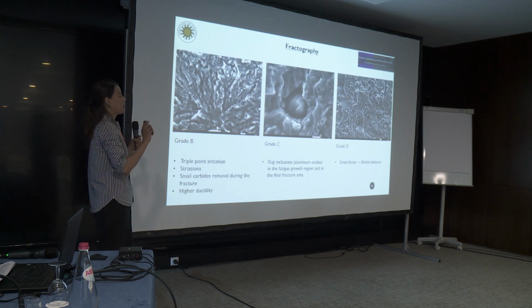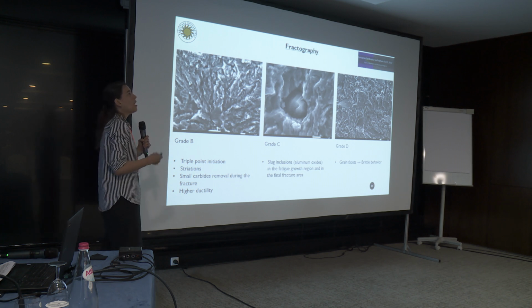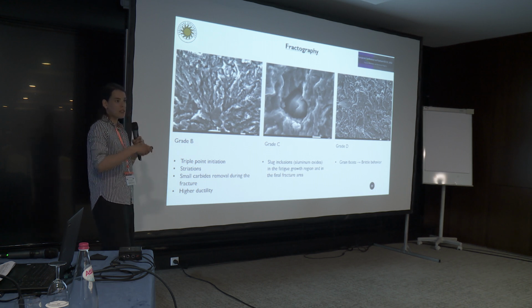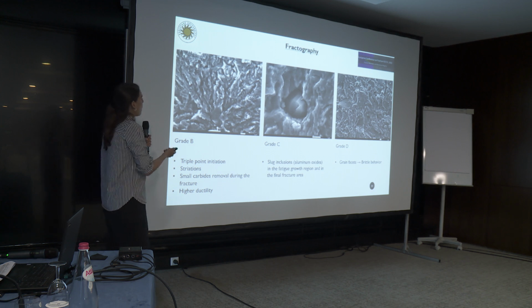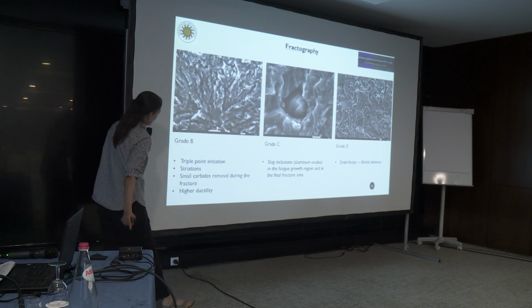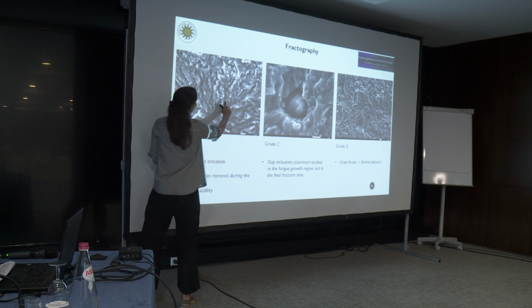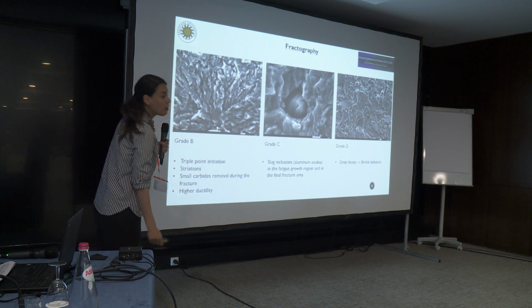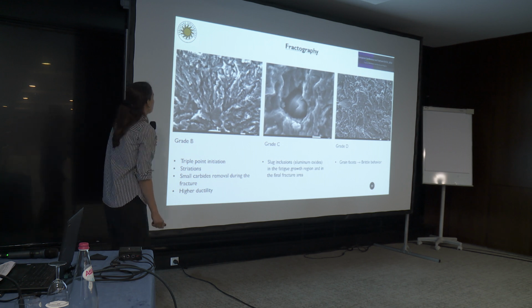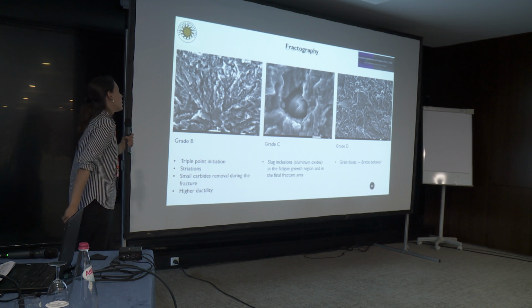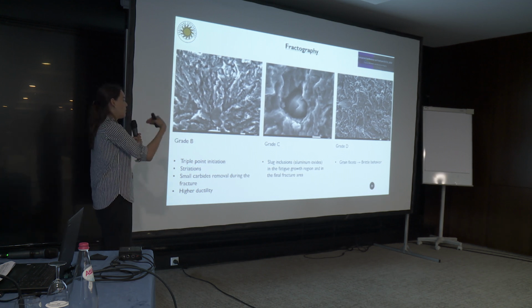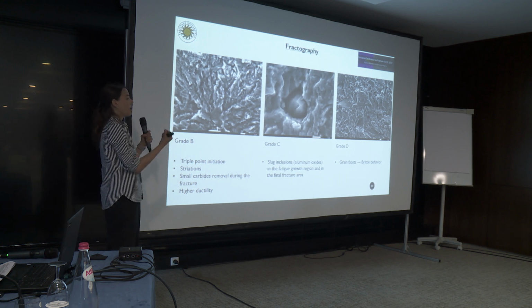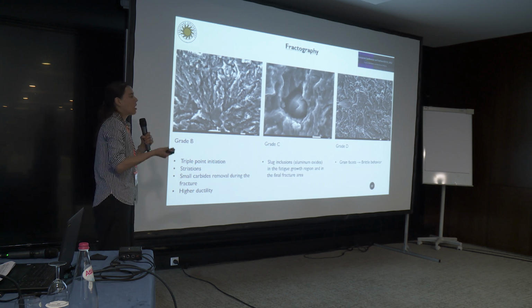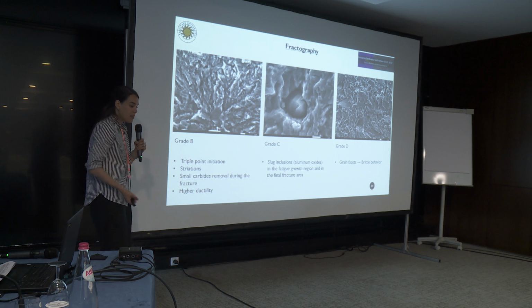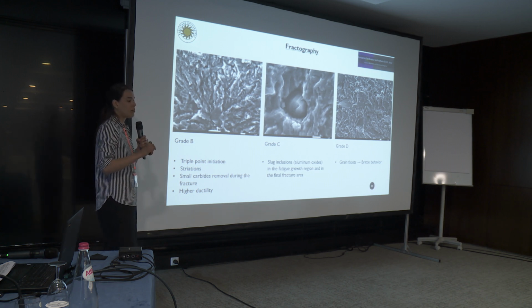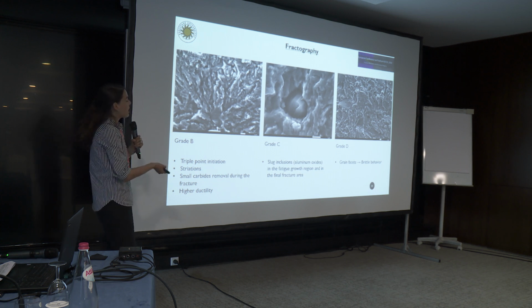In more detail, we have seen all the fractured surfaces, and we have found different packages of characteristics for each grade. So grade B, the carbon steel, we have seen triple point initiation similar to that one. There are striations around the initiation point, especially somewhere here, but since you cannot see them, you should trust me. There are some microvoids, like here, which are probably small carbides that were removed during the fracture, because they have the same size and shape as the carbides we saw during the microstructural analysis. Based on my experience with the testing, I can say that grade B had a little bit better and more ductile behavior than grades C and D.